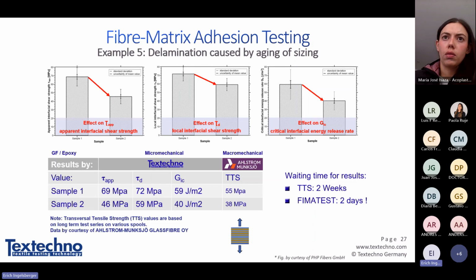We could prove by our FIMATEST system that there is an effect of aging of the sizing. They had even received a wrongly labeled sizing, so they put a wrong sizing on their fibers. It would be a good idea to use our FIMATEST system as an incoming quality control measure to see if the sizing is as expected. There is an effect of the sizing on the apparent interfacial shear strength based on the maximum force, on the local interfacial shear strength, and on critical energy release rate.